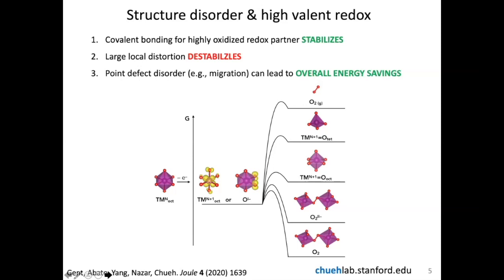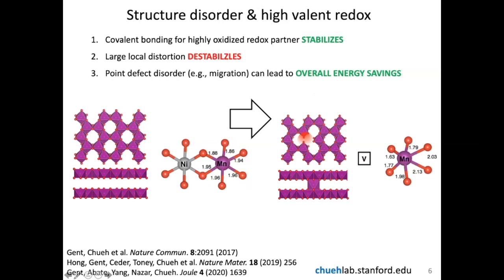And let me be more specific here. Let me give you the example of the lithium-rich NMC material. On the left of the screen, I have the fully delithiated material in which the atoms are in their perfect location. You can see on the top view and the side view, all the lithiums have been removed. Now when we oxidize the material to a high oxidation state, the bond between nickel and oxygen or manganese and oxygen will want to shorten. But because all the atoms are in their perfect position, the energy penalty is very high because there's no flexibility in the edge sharing structure in the layer oxides. So this is the destabilization caused by the distortion of the bond.